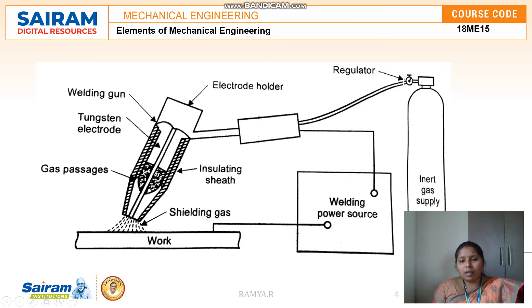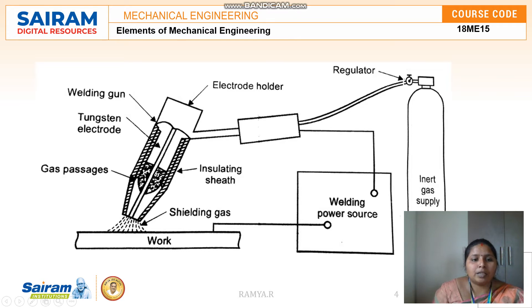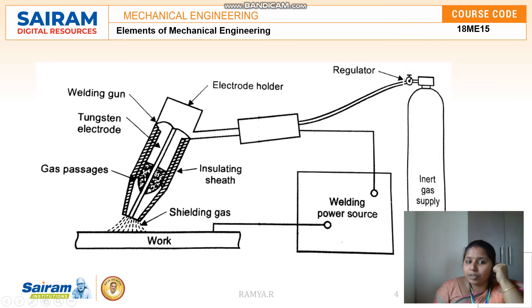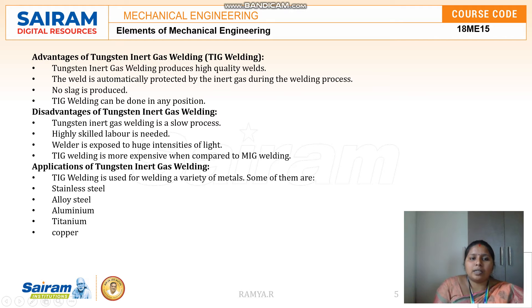When the power supply is switched on, the electrode holder is brought near the work piece while maintaining a gap of 1.5 mm to 3 mm. The inert gas supply does not react with the atmosphere, so it is used to protect the surface of the work piece. This inert gas is also sent inside the electrode holder. This is how Tungsten Inert Gas welding works.